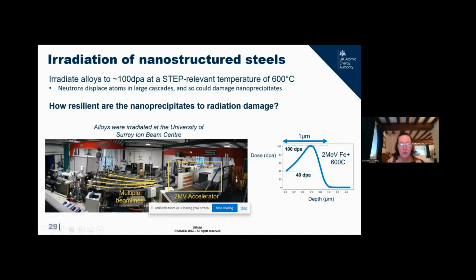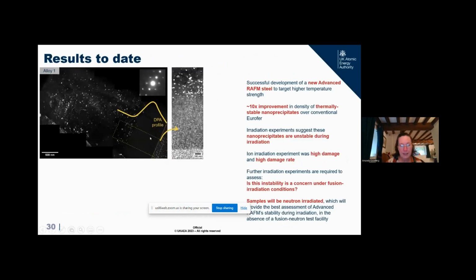Our next step was then to take some of those samples and irradiate them at the Surrey Ion Beam Centre at the accelerator there, and see if we could push it to 100 displacements per atom, a considerable amount of damage at a very high rate of damage, up at 600 Celsius. This is the kind of operating temperature we're now pushing for, and see what happens to those materials. And what we can see is in a profile, and here is the surface of the material, and this is the depth down into the material, and this is the DPA profile superposed. And what you can see there, rotated and expanded, is that we've lost our precipitates in that very high damage zone in our first results.